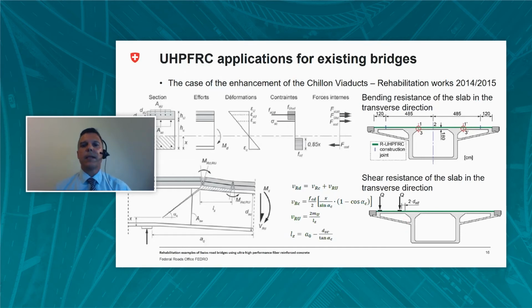With an angle of the inclined crack estimated at 35 degrees, the shear resistance of the composite section is 265 kilonewton per meter. The contribution to this resistance of the ultra-high performance fiber reinforced concrete is about 1/3 of the total resistance. The study has shown that in this particular slab, the flexural failure mode is much more likely to occur, also in the case of a shear-prone loading situation.